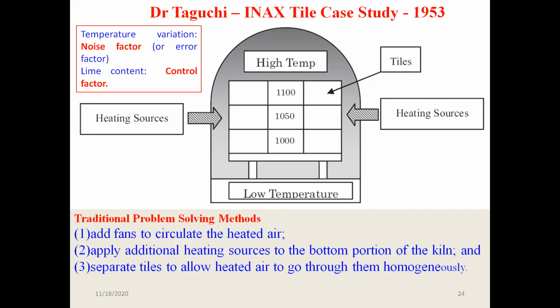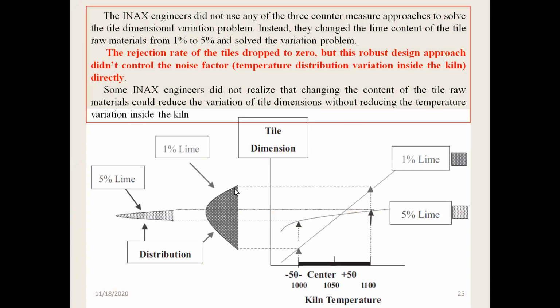With 1%, we had a lot of variations like this, almost this much. With 5%, we have only this much. So the recommendation was, in all the compositions, you add 5% of lime. No matter what the temperature variation is, you'll always get a nice result for the thickness variation. So that is the first successful case study on the design of experiments. It was performed by none other than Dr. Taguchi in a company called INAX.